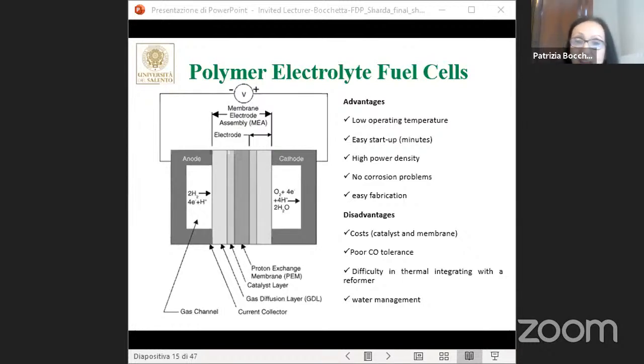In general, what are the advantages of this type of fuel cell? The low operating temperature, the easy and fast startup, thanks to the low temperature, high power density, no corrosion problems due to the use of polymeric membranes and also to the low temperature, and an easy fabrication. The disadvantages are located in the cost, because the commercial electrocatalysts and membranes are really expensive, and because the commercial catalyst is platinum. Platinum has a poor carbon monoxide tolerance, and also there is the need to have water management inside the cell, because we need water to have high proton conductivity.